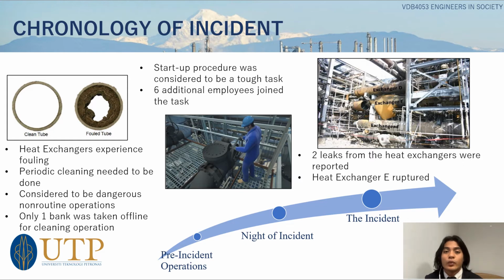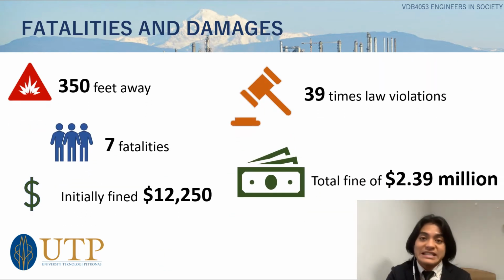Based on the figure below, we can see that the shell of the heat exchanger at the weld expelled a large volume of very hot hydrogen and naphtha. The naphtha and hydrogen released from the E heat exchanger into the atmosphere likely auto-ignited, creating a large fireball. The impact of the rupture was felt by the inside operator in the NHT control room, located 350 feet away. All 7 outside operators were severely burned, and all of them lost their lives within 22 days of the incident. The Tesoro Refinery had been fined in 2009 for 17 serious safety violations. Those fines were later reduced to 3 violations and cost about a $12,250 settlement.